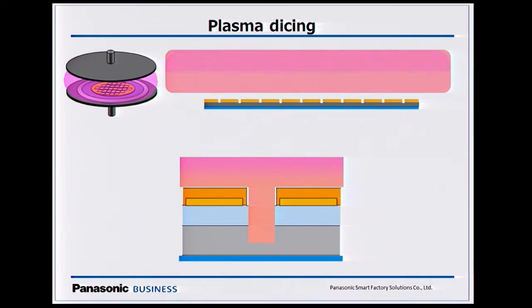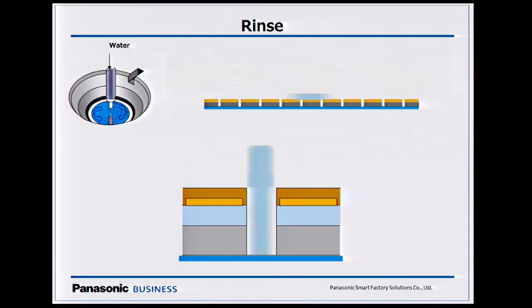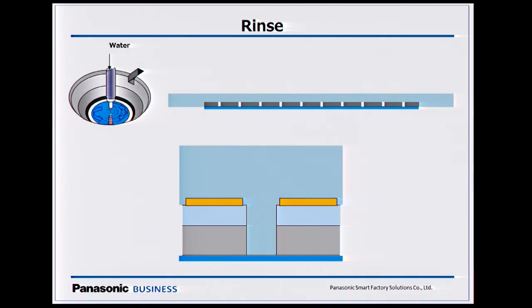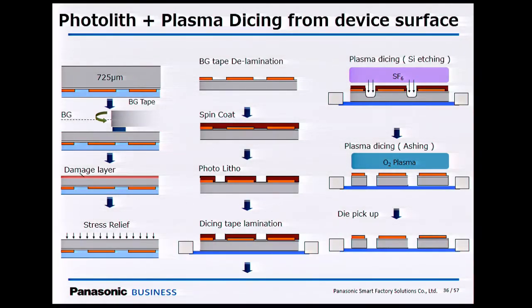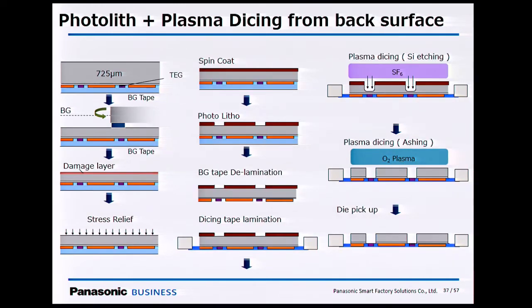You put it inside the dicing chamber with the appropriate recipe and dice through the wafer down to the dicing tape. And then rinse or ash. In this case, it's a water-based resist, so it's quite simple, but you can also use O2 plasma inside the dicing chamber to remove this photoresist. And now you have a conventional dicing frame and tape with a singulated wafer. That's the basic concept. This is just a schematic of all those steps again. There's the added step, which is not in the video, of a stress relief step. This also highlights that you can use O2 plasma to ash the resist off. And if it's not possible to etch from the top of the device, the wafer can basically be flipped, and the same approach can be performed from the backside.